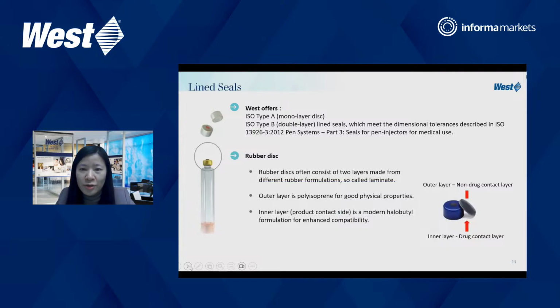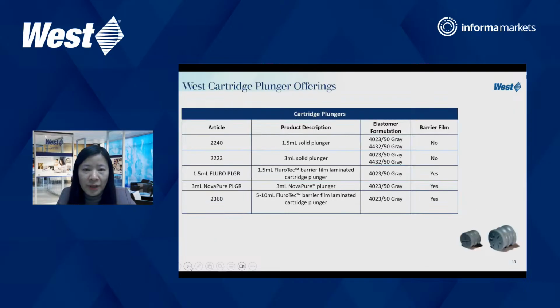As just mentioned, both mono-layer line seals and double-layer line seals are available from West, and they can meet the dimensional tolerances described in ISO 13926. The double-layer line seals contain different rubber formulations for the 2 layers. The outer layer is a non-drug contact layer, formulated with polyisoprene, and the formulation features excellent physical properties, so it can meet the requirements for multiple punctures. The inner layer is a drug contact layer, formulated with modern halobutyl formulations for enhanced compatibility. Next slide, please.